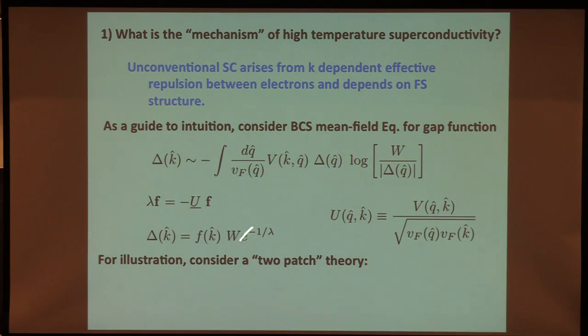Okay, now, I want to look at what the solution of this problem looks like. And for simplicity, let's imagine that there are two pieces of Fermi surface that are important, two patches, two values of K and K prime. And we'll imagine that U has some value called U small if we're scattering between vectors that are part of the same patch of Fermi surface, and some other value called U large, which is what we get for scattering between pieces of the Fermi surface that differ by a large amount of momentum.